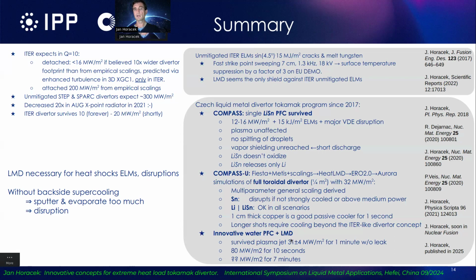So either liquid metals or, I would say, together, that would be the best: the innovative water-cooled plasma-facing component together with liquid metals, because liquid metals are the only way to sustain extremely strong heat shocks, like transients, disruptions, and ELMs, and combined with water-cooled innovative plasma-facing components, they should sustain also the long-term operation, because otherwise they would evaporate and sputter too much if the surface is not cooled as strongly as possible.